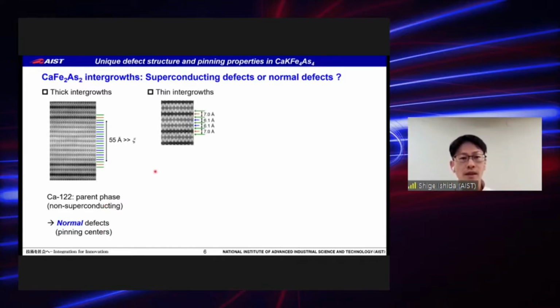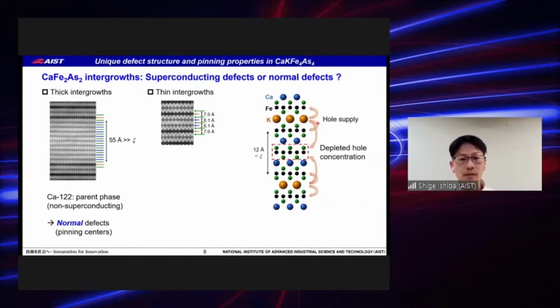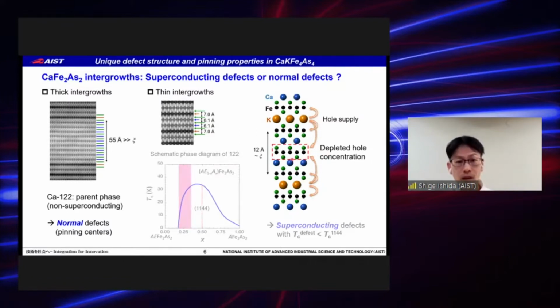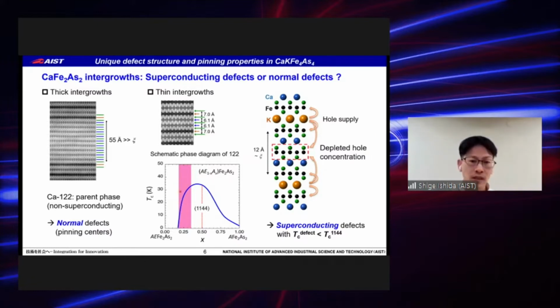On the other hand, in the case of thin monolayer intergrowths, holes are expected to be supplied from the potassium layer, although it is a bit away from the iron arsenic layer. Comparing with the phase diagram of the 122 material, although the hole concentration should be depleted compared with the 1144 matrix, the monolayer calcium 122 is probably superconducting, and the TC of the defect is expected to be lower than the TC of the 1144 matrix.